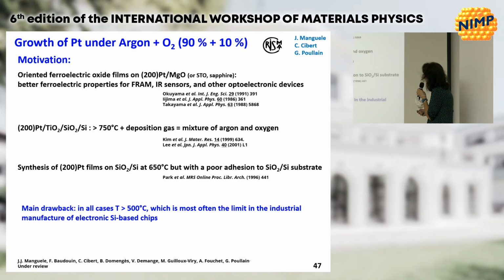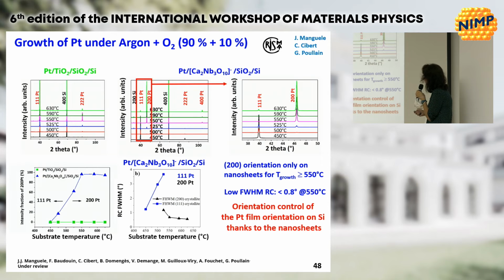Some attempts were also made to obtain the film at a lower temperature, but without this adhesive layer, and then we have poor adhesion to the substrate. So in all cases, the temperature is very high. So here the idea was to try also with nanosheets and see what happens. And on the normal substrate, nothing special happens. We still have this 111 direction.